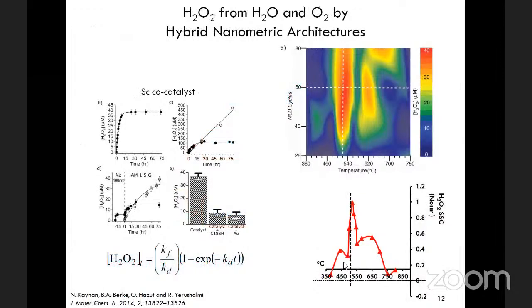This is how it looks. We did a very thorough study where we studied the performance towards hydrogen peroxide production with anneal temperature of the catalyst and number of cycles, which means the thickness of these oxide tubes. And you can see that there is a very prominent activity peak at 520 degrees Celsius here. And also there is some threshold of thickness where activity begins, and you can see it here. This is how this cross-section looks.